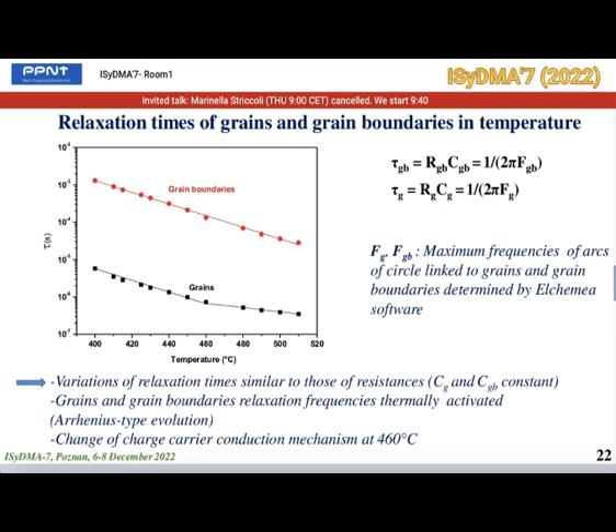Here we have plotted the relaxation times of grains and grain boundaries. They are calculated from resistances and apparent capacitances. They have a similar variation in temperature to those of resistances, since apparent capacitances are constant, as seen on the previous slide. They also show an Arrhenius type evolution with the change of slope at 460 degrees, indicating a modification in the conduction mechanism of the charge carriers in the grains.